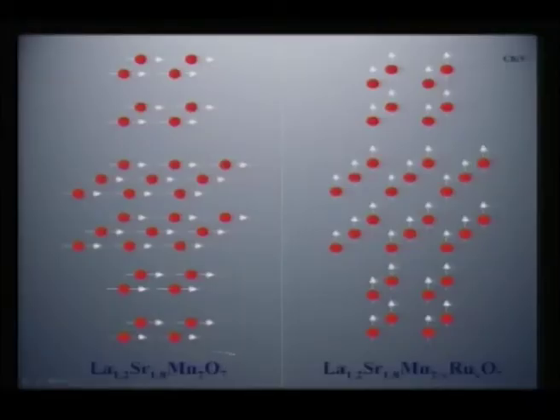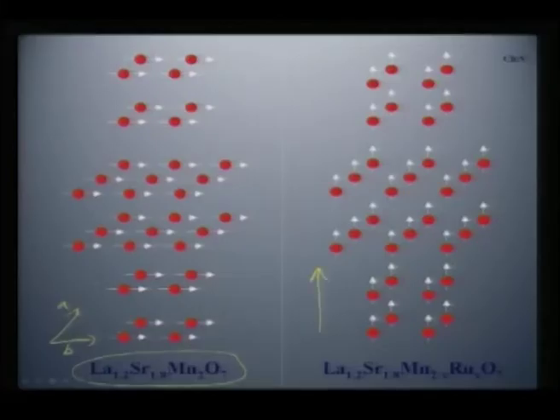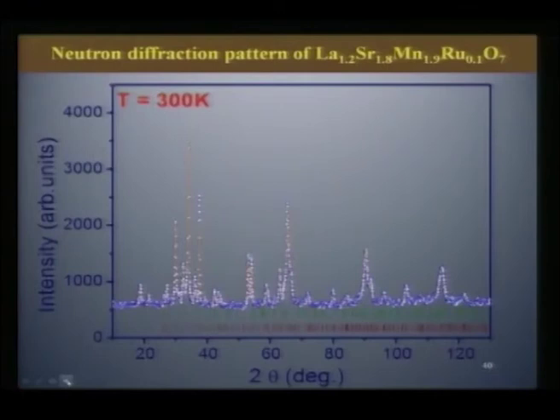You can see here the spin orientation of the manganese core spins are actually confined in the AB plane, whereas when you substitute ruthenium, the neutron diffraction studies clearly tell us that there is a rotation of the spins along the C direction. It is no more confined in the AB plane, it is now coupled in the C axis. Now, when it is coupled in the C axis, this can promote or enhance your ferromagnetic ordering and your metal insulator transition. It is not a guess, we can see that from the neutron diffraction case.